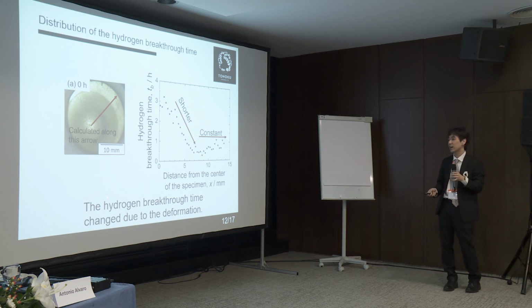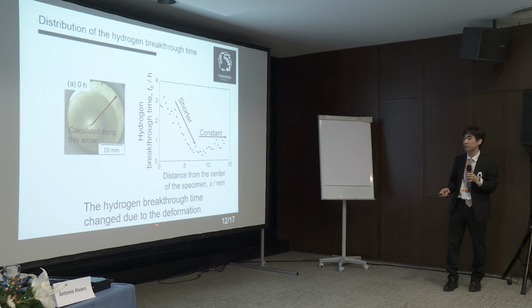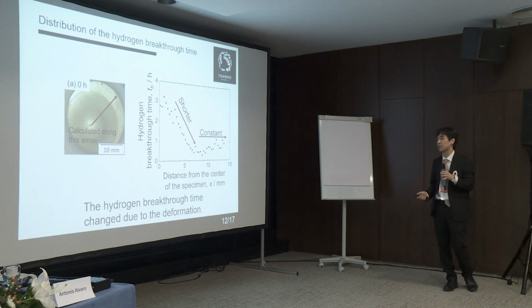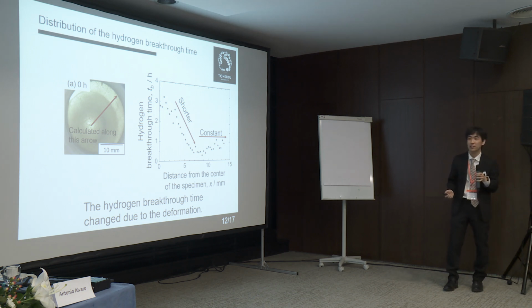So you can see the hydrogen breakthrough time was clearly changed due to the deformation. And we can say that the hydrogen visualization technique using iridium complex is able to be applied to a non-flat specimen.